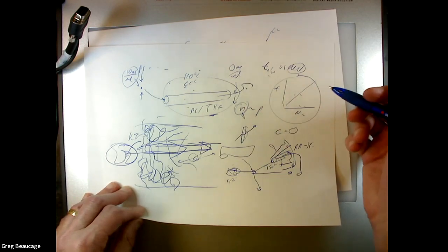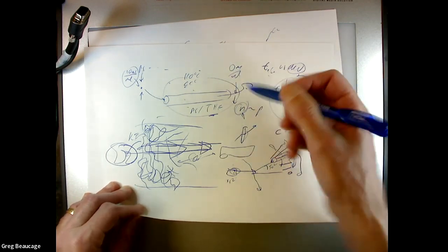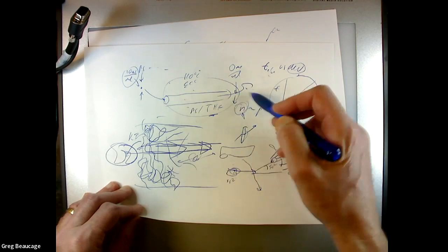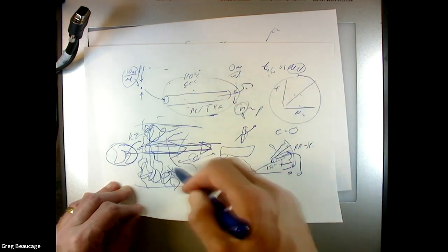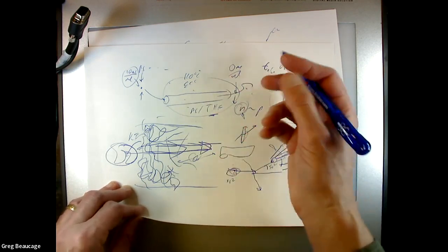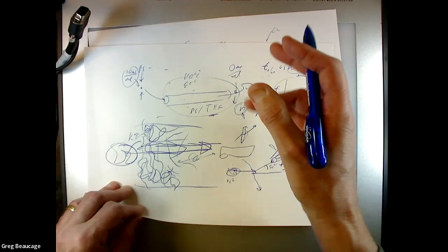But if you combine those, you can tell a lot about what the structure of the chain is, because the different techniques look at different things. Like the viscosity detector looks at the hydrodynamic radius, the drag coefficient, which changes if it's branched, while the light scattering gives you the molecular weight.